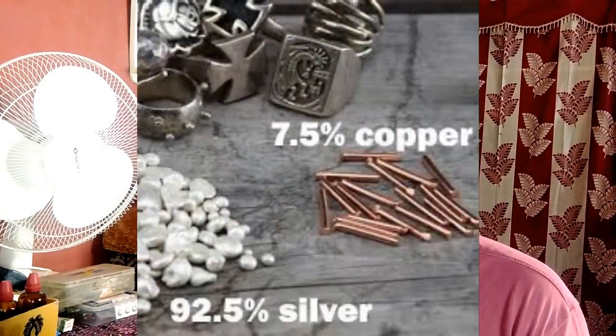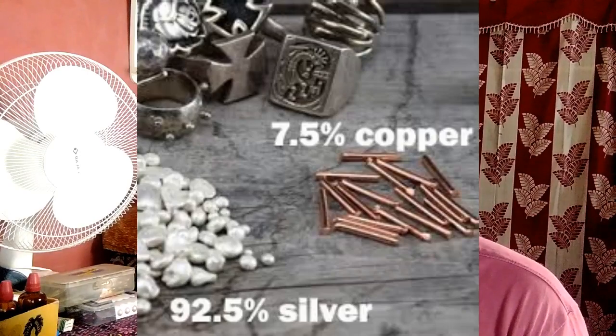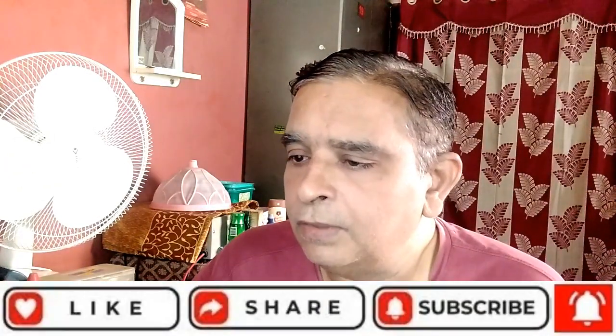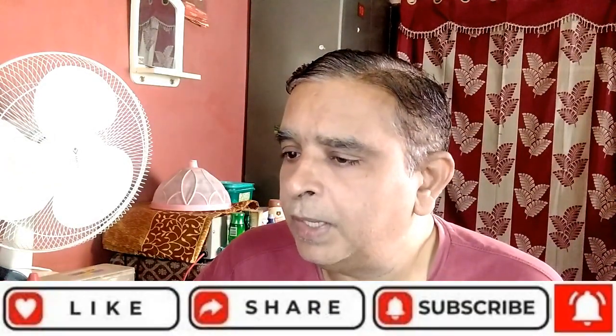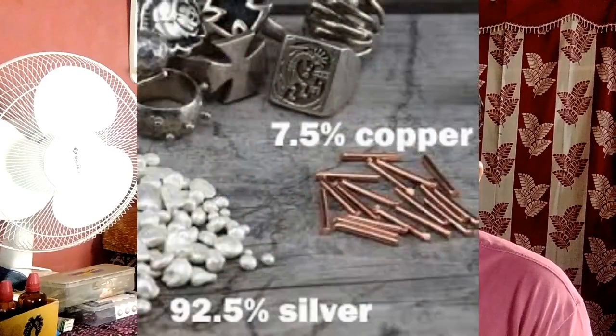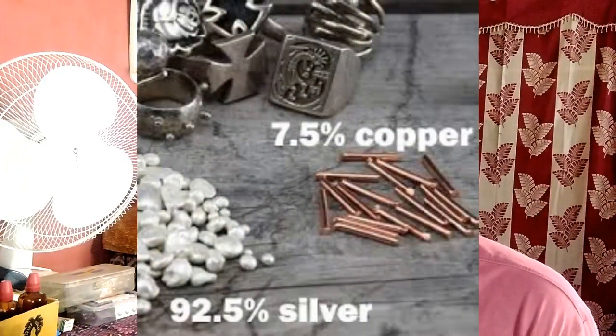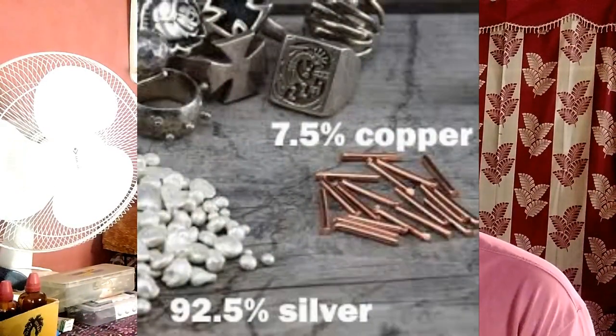Other methods of recovery are activated carbon absorption, where solutions are pumped through tanks or towers containing activated carbon, and the addition of a sodium sulfide solution which forms a silver precipitate. In another method, the solution is passed through charged resin materials which attract the silver. The recovery method is generally decided based on technical or economic factors.